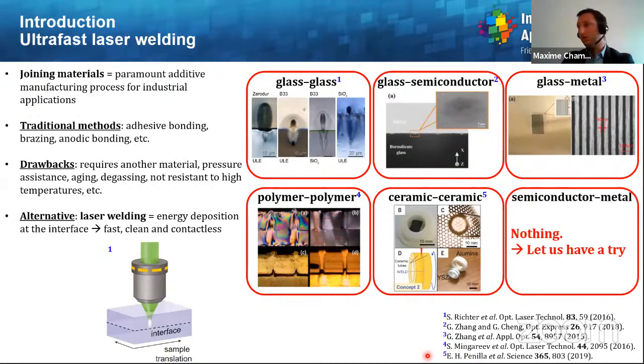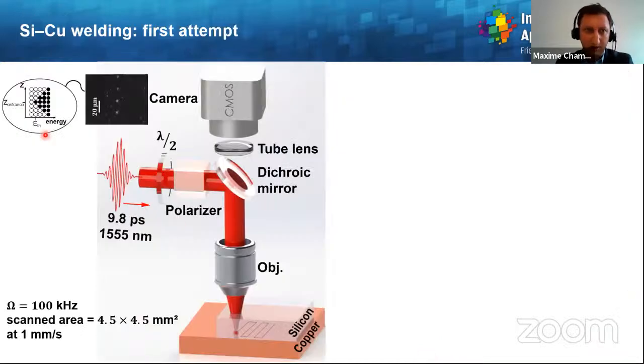However, in the semiconductor-metal configuration, there is nothing too convincing so far. So let us have a try together. To do so, we'll employ the following setup, which again relies on 1.55 micron wavelength and around 10 picosecond duration laser pulses. Then we adjust the energy classically with a half-wave plate and a polarizer before the beam is focused at the interface between silicon and copper by means of an objective lens.